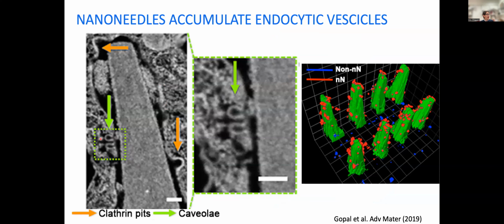So one important element in the delivery is the interface. And as you can see here, and as I have anticipated, you can clearly identify that these structures do invaginate the membrane significantly, and they specifically induce extracellular vesicles and endocytic vesicle formation around individual needles. And we think that these play a significant role in the delivery of cargo from the needles to the cells.